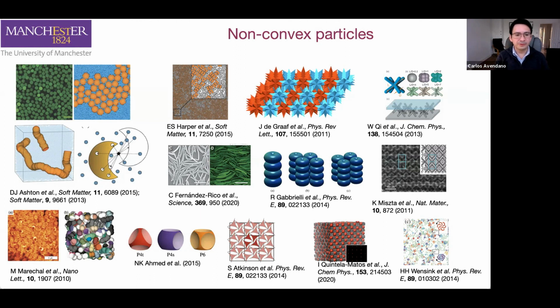Non-convex particles are a little more complicated. For example, particles with branches are not a problem, since this model has been designed with spherocylinders. But in the case of rings, say you're trying to obtain the phase diagram of something like cyclohexane. You imagine having two cyclohexanes and you make a Monte Carlo move. It's always possible, because this is a non-physical move, that they will interlock completely unphysically, like taking two rings and interlocking them. But that's not possible. How to prevent that from happening in the Monte Carlo code is not simple. You need to somehow devise a mathematical algorithm to prevent that kind of interlocking.